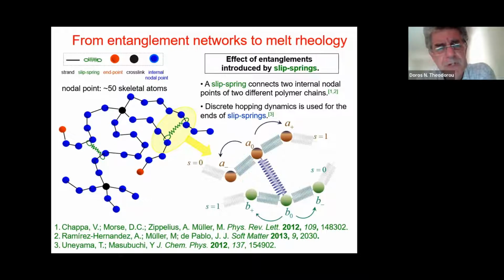When a slip spring reaches a chain end, it may choose to jump out of the chain, in which case we'll lose the entanglement. However, continuously, chain ends try to entangle with other chains in their surroundings. And again, this is also viewed as an activated process characterized by a rate constant. So at equilibrium, you have an equilibrium concentration of entanglements or slip springs as a result of these destruction and creation processes of the slip springs.